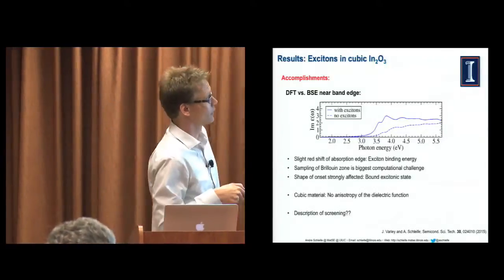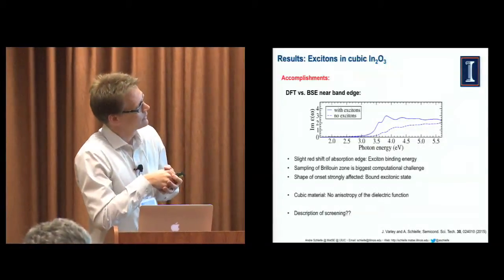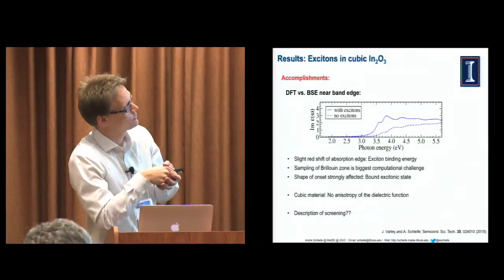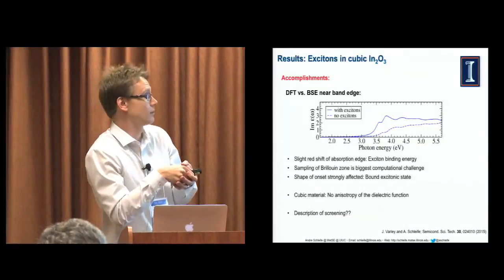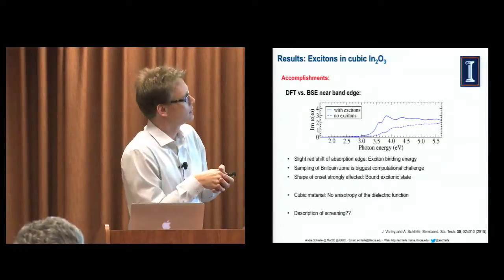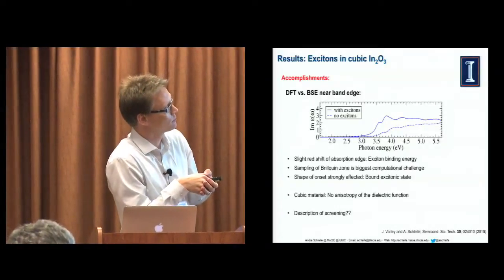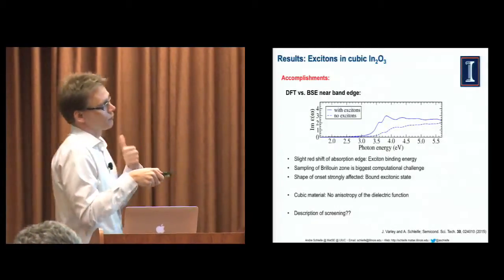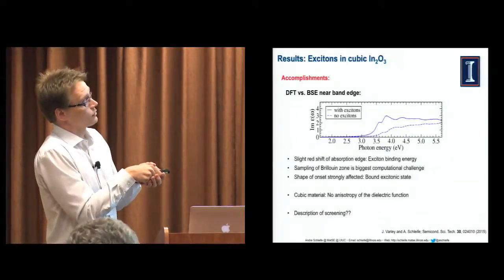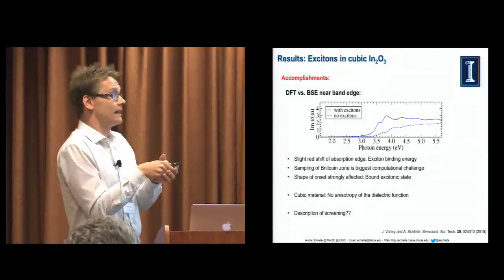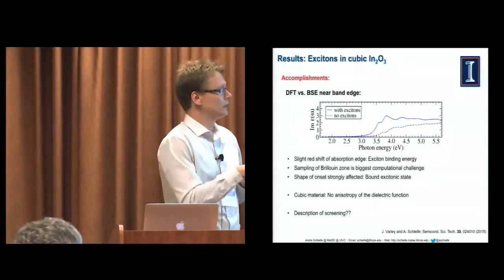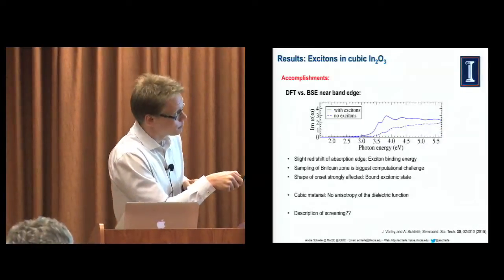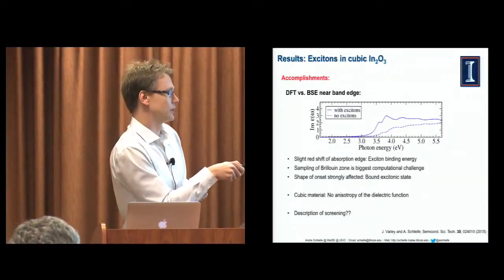So the first curve that I want to show you is actually kind of a zoomed-in version of the spectrum close to the absorption band gap, right? The band gap of the material. So the dashed curve is without excitons. That is what I showed you before for magnesium oxide. And the influence of excitons is now large, right? We get a large deviation. That is something you can definitely see in experiment. So we see this pronounced enhancement of the absorption onset.